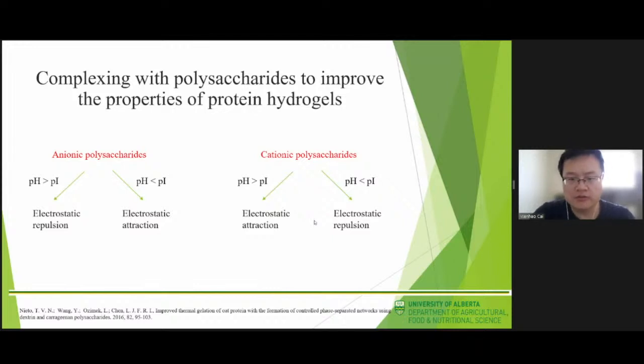Using negatively charged polysaccharides as examples, when pH is larger than the protein isoelectric point, repulsion exists between protein and the polysaccharides when they are both negatively charged. A phase-separated network can be formed, with one network rich in protein and the other rich in polysaccharide, caused by the incompatibility between these two polymers due to the repulsive force and the varying affinity towards the solvent. The increased apparent protein concentration, as the result of protein exclusion from the space occupied by the polysaccharide, promoted protein interaction to develop a stronger gel network.